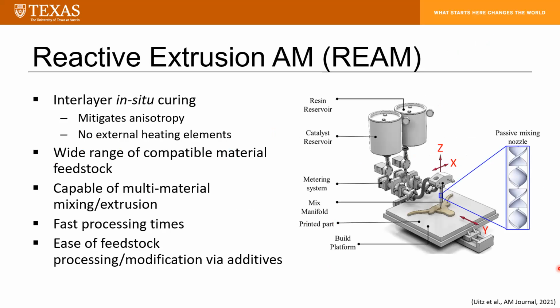So REAM is an additive process that makes use of a two-part thermoset resin. So you have your catalyst reservoir and your resin over here. They are metered at the appropriate volume ratio and then pumped through a static mixing nozzle, which induces turbulence in the flow, mixing your resin and your catalyst together. The material is then deposited and allowed to cure in situ.